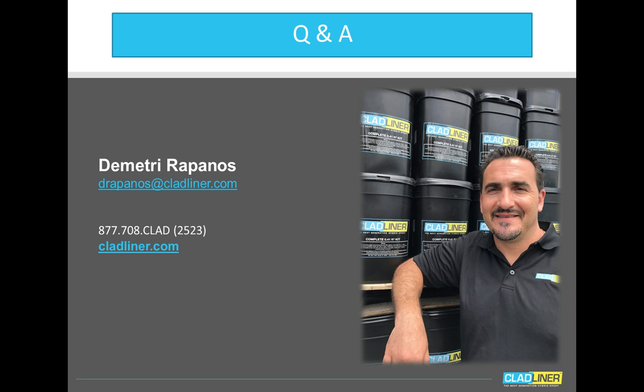Other than resistance to acid, how do the mechanical properties, strength, adhesion, crack resistance of hybrid epoxy compare to standard mortar and epoxy? It stands up really well. The PSI compressive strength is, I believe, just under 10,000, which is very high. As far as the crack resistance and adhesion goes, the epoxy itself gives it a much, much better adhesion than any traditional cement will give you, because the epoxy itself creates a stickiness or adhesive property to the cement.